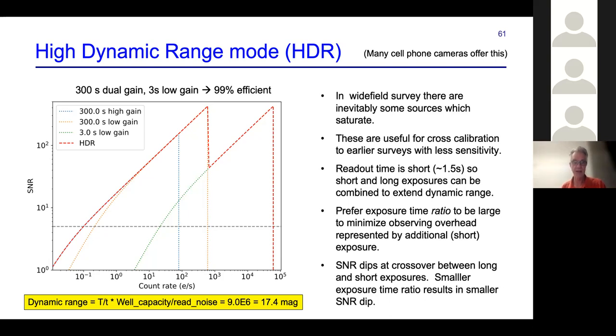And this particular example, which I've drawn here, which shows signal to noise versus signal level, is showing that in fact we have effectively a dynamic range of about 10 to the 7. And so combining the gain switching with this dual exposure time, we actually can get a dynamic range which is far greater than a CCD, even as we have 99% observing efficiency.